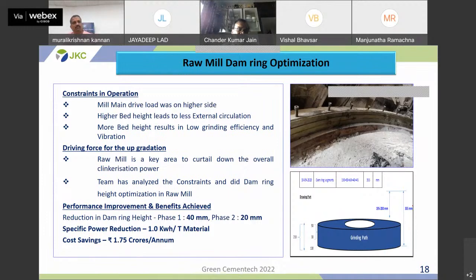Raw mill is a key area to reduce the overall clinkerization power, as raw mill power contributes 1.5 times in clinkerization power. We analyzed this problem and did dam ring height optimization in raw mill. By this, we have reduced our specific power consumption by 1 unit per ton of material and cost savings of 1.75 crores per annum.